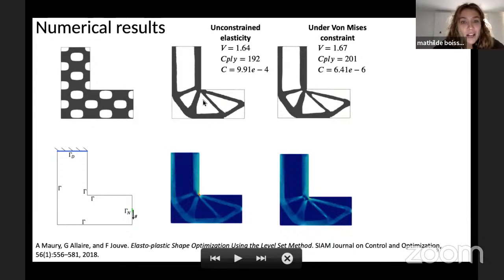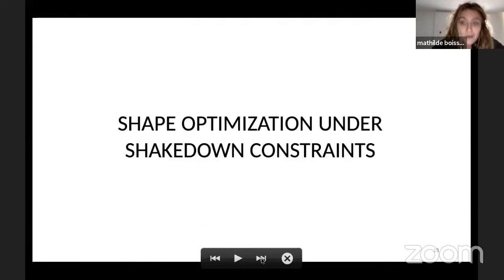So we have also the L bracket, which is another test case. You see that the problem for the L bracket is that we have a very high elastic stress in the corner here. And when you optimize adding the von Mises constraint, you see that the algorithm removes some material here so that it avoids these very high stresses. Now we can go to Shakedown.